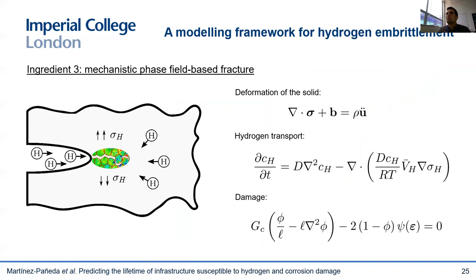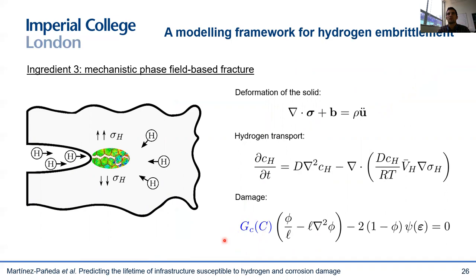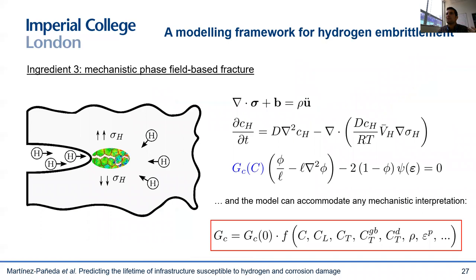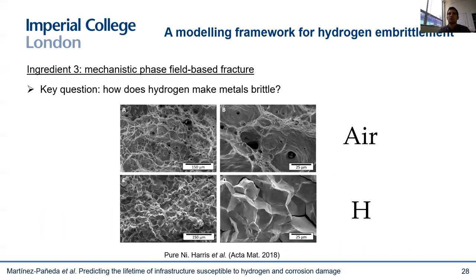The way to couple this with hydrogen is straightforward. What we see in experiments is that hydrogen degrades the material toughness, so we make the toughness GC dependent on the hydrogen concentration through a degradation function. The beauty of this approach is that it is universal, accommodating any mechanistic interpretation. One can define this degradation function to depend on the lattice hydrogen concentration, the total hydrogen concentration, hydrogen trapping at grain boundaries, or the dislocation density — or fit it empirically to experiments.